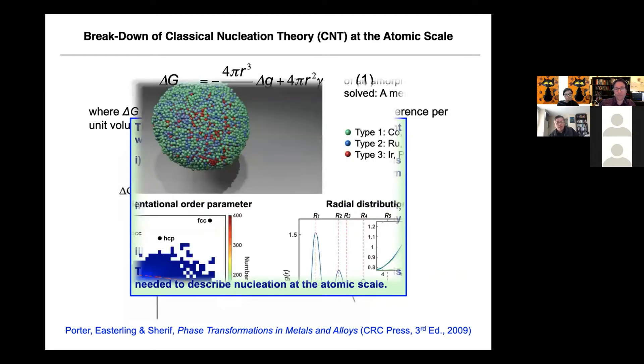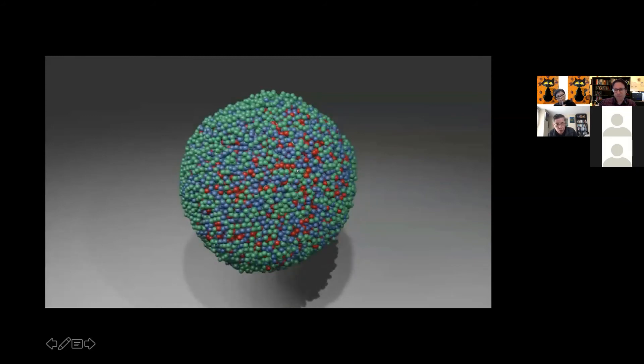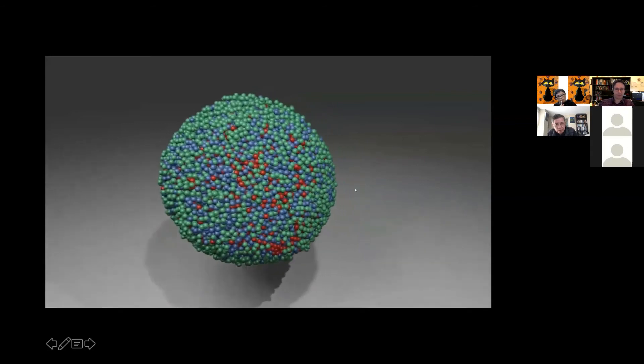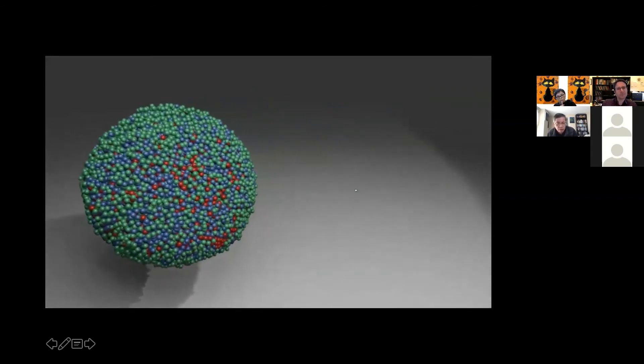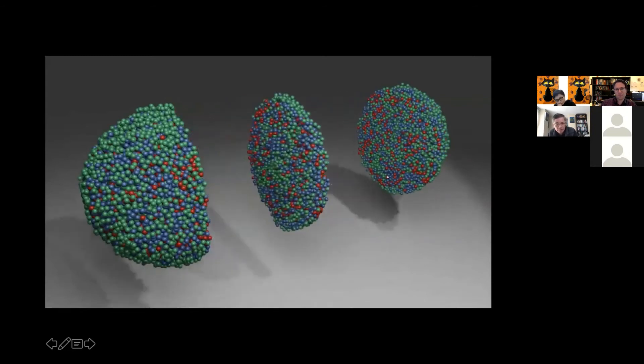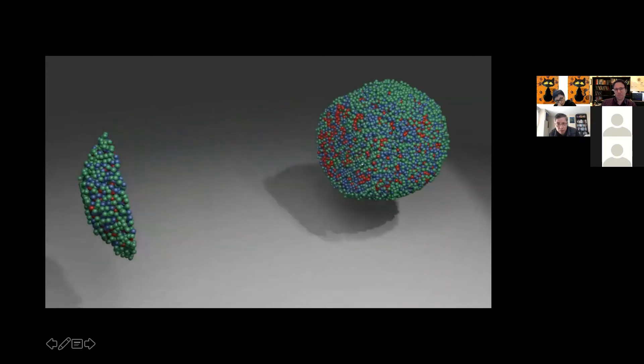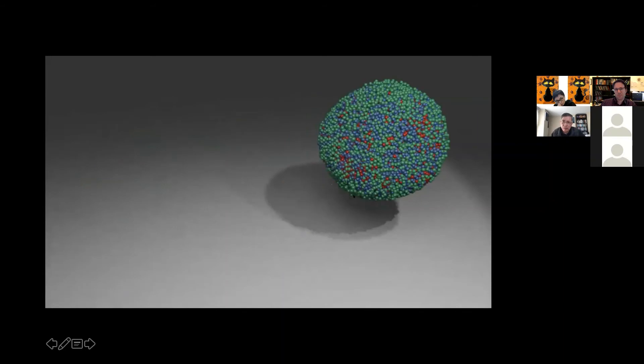Finally, I'll discuss our recent work just published a few weeks ago in Nature: determining the 3D atomic structure of an amorphous material — really for the first time, looking inside amorphous materials. This is one of the important directions for our HDR proposal. Here I'll show the movie: there are three types of atoms — red, blue, and green. Going slice by slice, most of the structure is more disordered, with some crystalline nucleus features inside the nanoparticles. But more than 85% is truly amorphous structure. The top sample has eight different elements — a multi-component metallic glass.